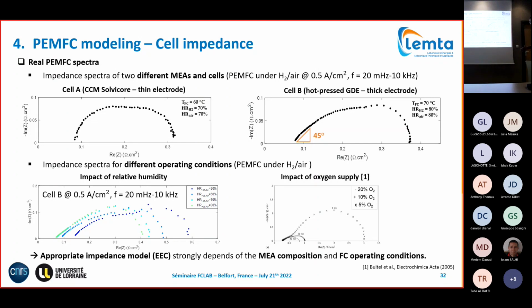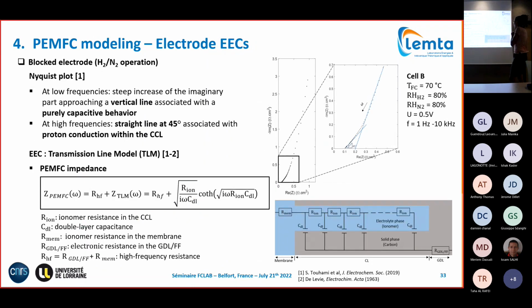Oxygen supply, your mass transfer, is a very slow process. So oxygen supply will play on the spectrum at low frequencies. The lower the oxygen supply, the more pronounced the half loop at the lowest frequency, and the higher the oxygen supply, the less pronounced. Okay, so the circuit that will be adapted to interpret the spectrum depends on the MEA and on the operating conditions. So that's really something one has to find: that circuit.